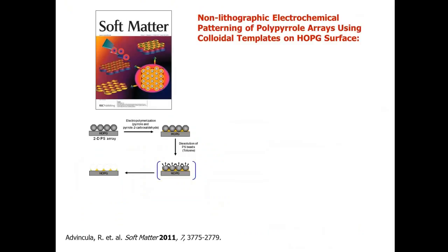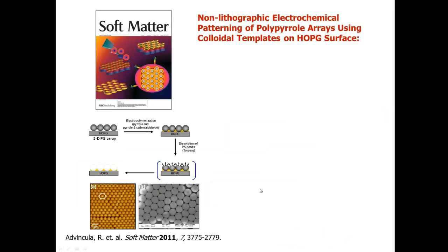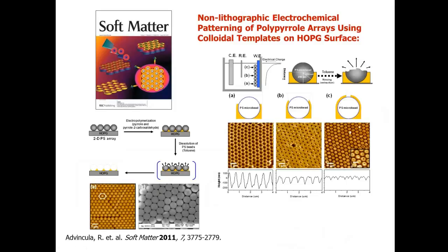An example is how we have used colloidal particles, which the coatings industry knows as binders, made up of emulsion polymerized polymers. Here we have two-dimensionally patterned them on surfaces, and we were able to electropolymerize around them such that we can preserve and obtain honeycomb structures. Now, these are very interesting structures in that we can do dual chemistry as well as smart surfaces for sensing, molecular printing.